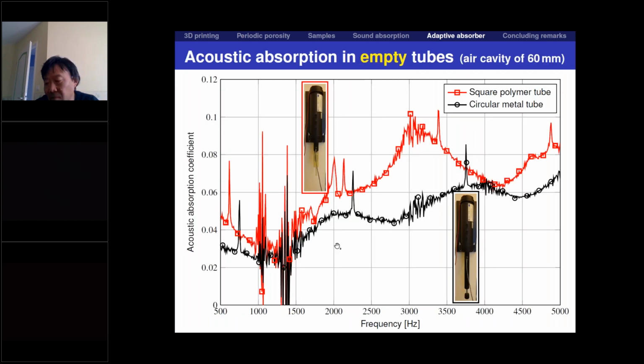And before measuring the samples, we checked that our square tube is not so bad, because here's the absorption in the empty metal tube and the empty square tube, and the absorption is sufficiently small. Obviously, theoretically, it should be zero, but there are some losses and leakages involved.